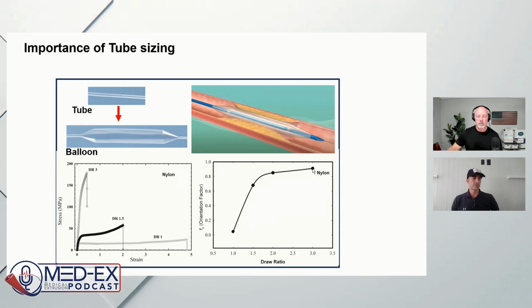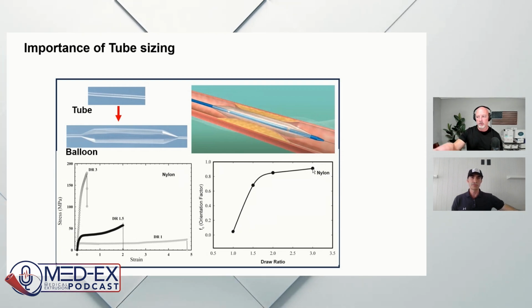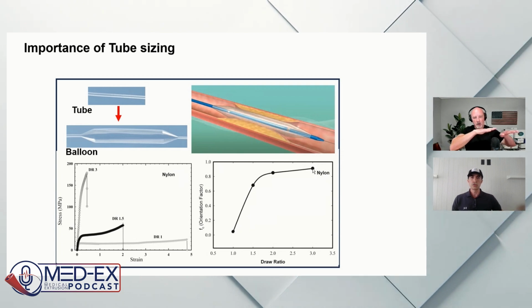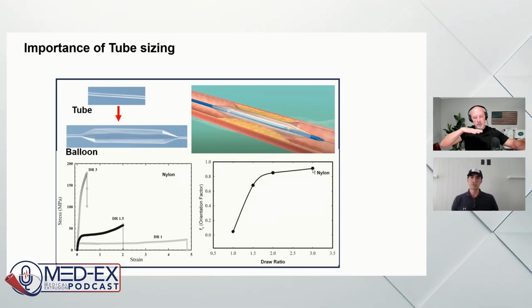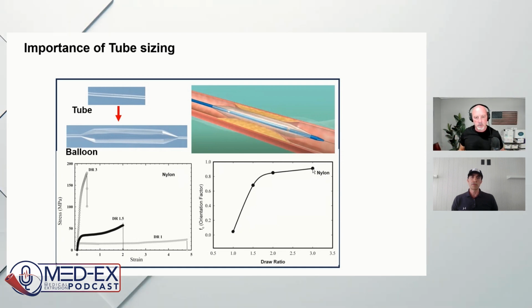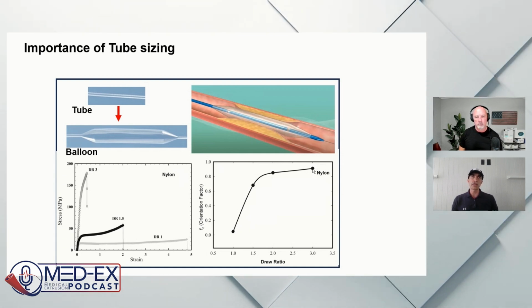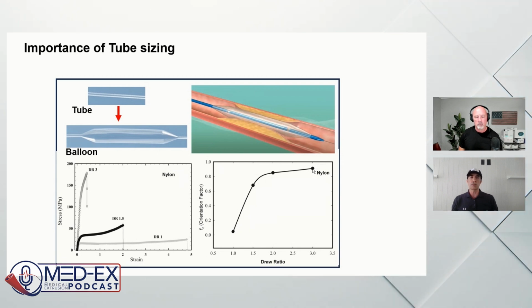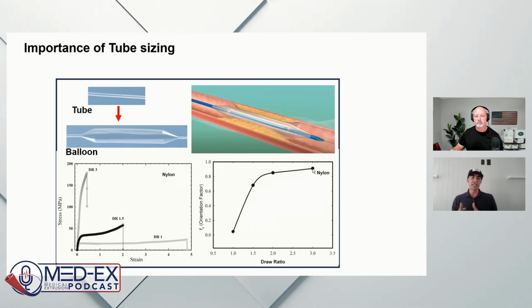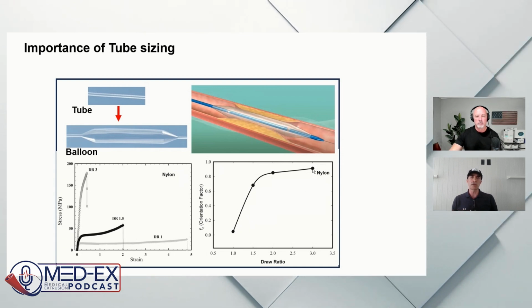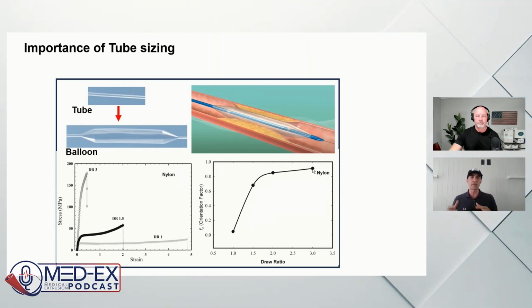For a soft compliant balloon, what are we talking about from a drawdown ratio? And are we also stretching a compliant balloon as well, a material like a TPU? Are we doing the same type of process? Yeah, it's the same. If you look at even the polyurethane balloon, there are also segmented polymers. That means they have hard segments and soft segments. Yeah, okay. The only difference is that the ratio of the hard to soft segment is different. They have more soft segment within that structure. So it's pretty much the same principle.